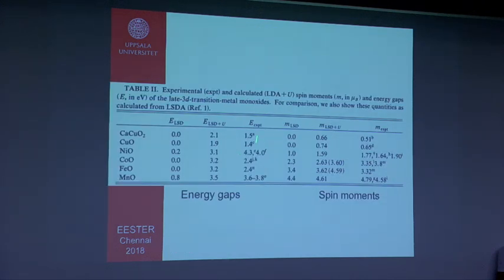Some comparison of magnetic moments here on the right hand side, or the energy gaps. One can say that there is reasonable agreement between experiment and theory, like this. Local spin density approximation is very bad in this respect. The energy gap as well as the magnetic moment is not so good in many cases, whereas the plus U and experimental results actually match pretty okay. I'm not claiming that this is the method one should use, because I guess you have been talking about how to choose U and all these things. There are certain methods to calculate U, and one has to use them with proper care.